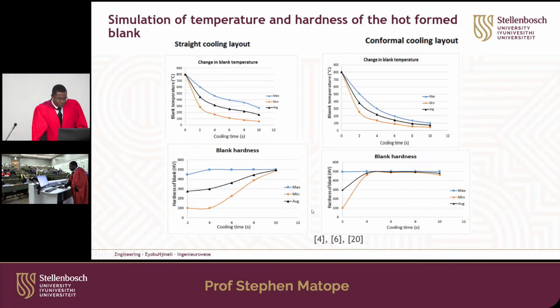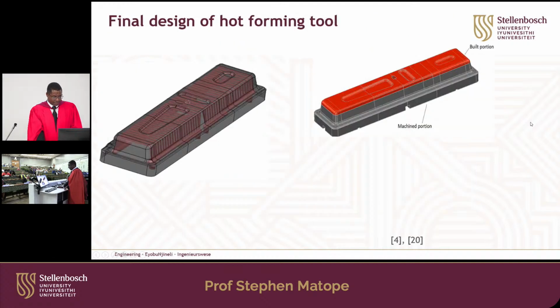Right, when it comes to the hardness, with the straight cooling layout, we found that 400 to 500 was difficult to reach, somewhere around 10 seconds. But with our conformal cooling, we found that it can be reached after 5 or 4, so somewhere after 5 seconds we can reach the Rockwell hardness number of 500. Having done that, we were then sure that we can start building our tool using additive manufacturing.